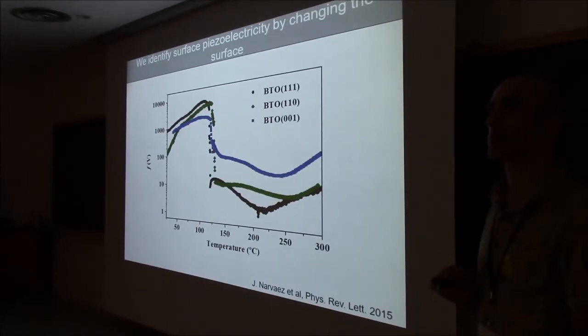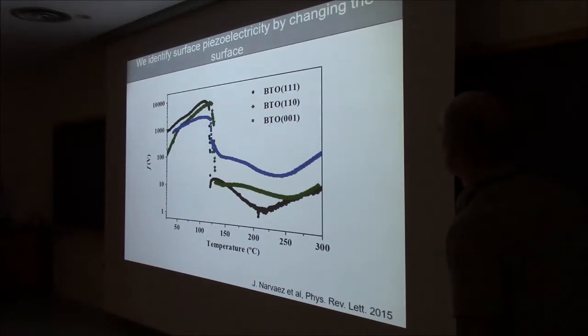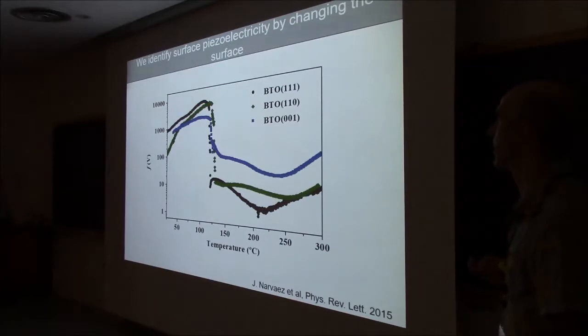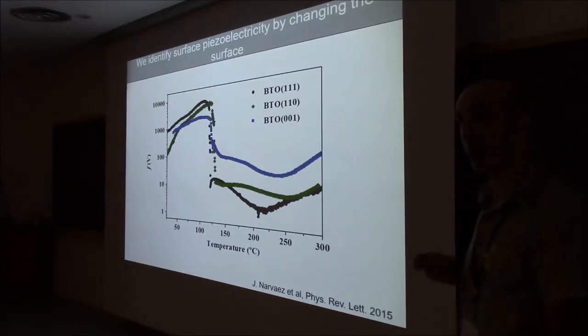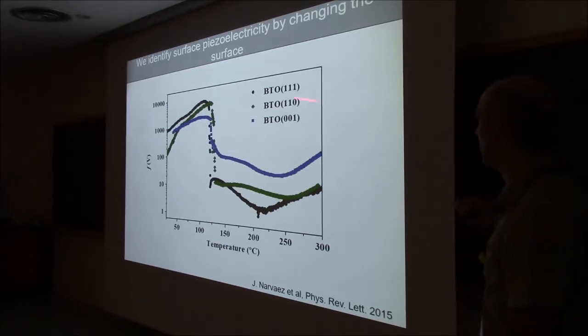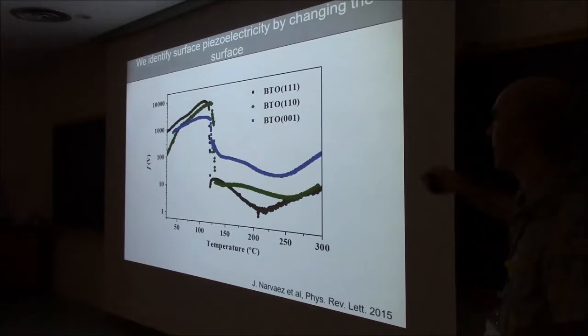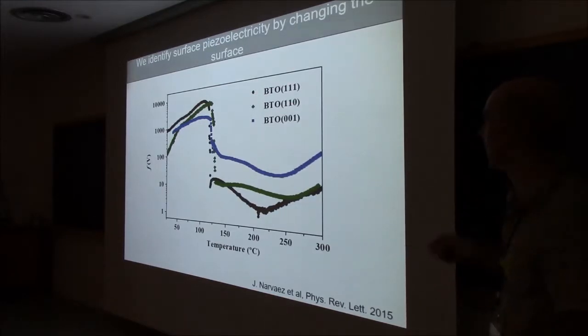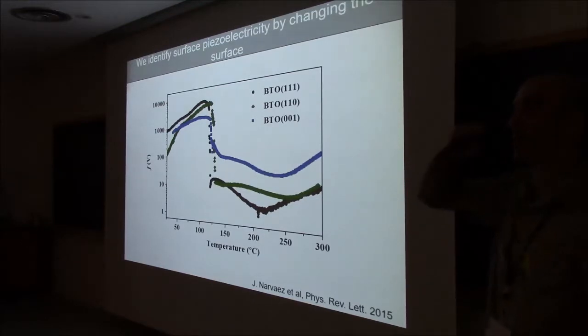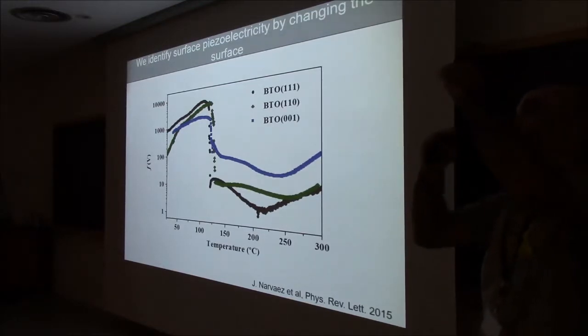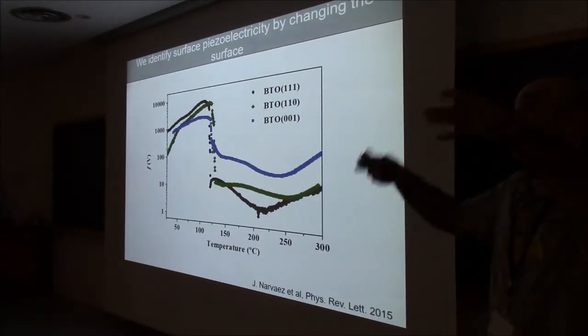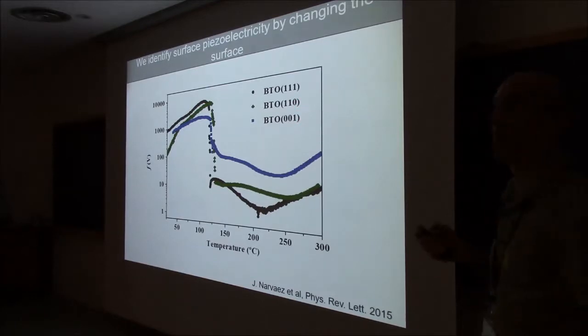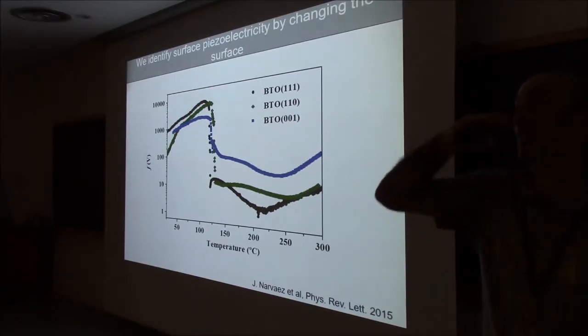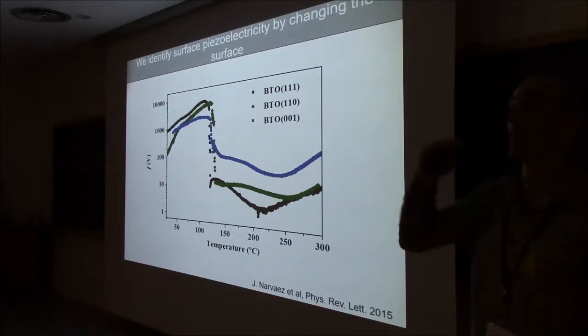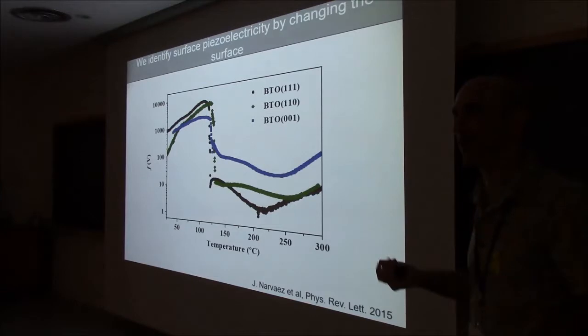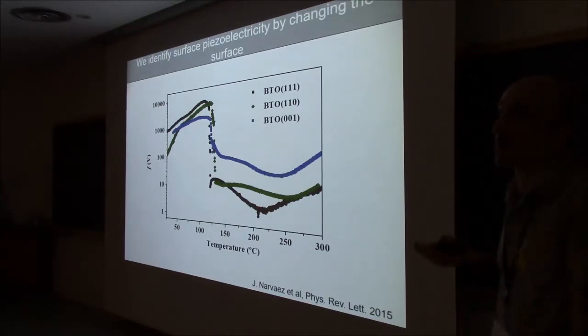Connecting to the same question, do you have a qualitative explanation why the 111 seems to have a smaller coefficient than the 001? No, and in fact it's exactly the opposite of what I expected. If you're familiar with the perovskite unit cell, the 001 planes are charge neutral. Either titanium dioxide or strontium oxide, thinking of STO, are charge neutral, have charge 0. The 111 planes will not be charge neutral. It has a lot of charge, the last surface termination. So I expected that if you had a surface that is very charged, it will also be very surface piezoelectric. Experimentally, that doesn't seem to be the case.